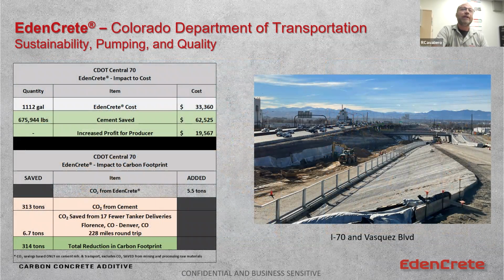And the use of EdenCrete ultimately provided the producer $20,000 more, more money in their pocket. We saved 675,000 pounds of cement from the job. Ultimately, CO2 from EdenCrete only contributed 5.5 tons to the entire project. And when we look over here on the left, we saved ultimately 314 tons of CO2 from the Central 70 project, simply because EdenCrete makes it creamier and we could reduce cement and drop it 152 pounds per cubic yard. And now Central 70 has a carbon footprint story to it.